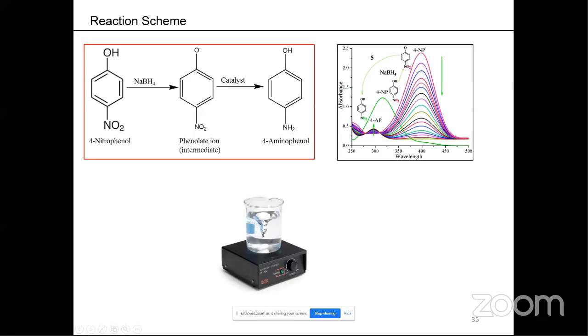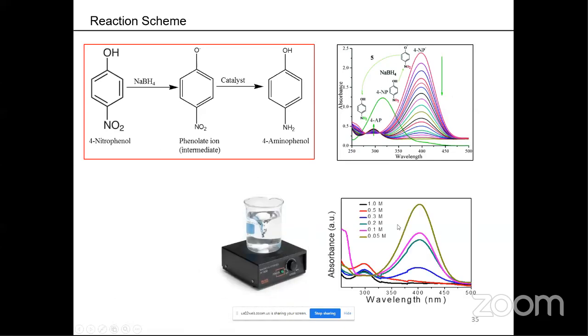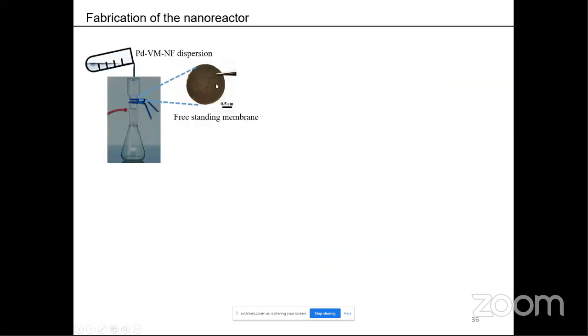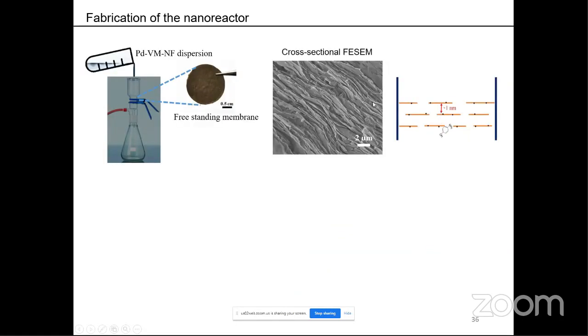First, we tried our catalyst in the stirring condition to see whether the catalyst works or not. Yes, you can see that with increasing sodium borohydride concentration, the concentration of the phenolate ion decreases. That means the reaction takes place. Now we have made a membrane out of our catalyst, and made this confinement.